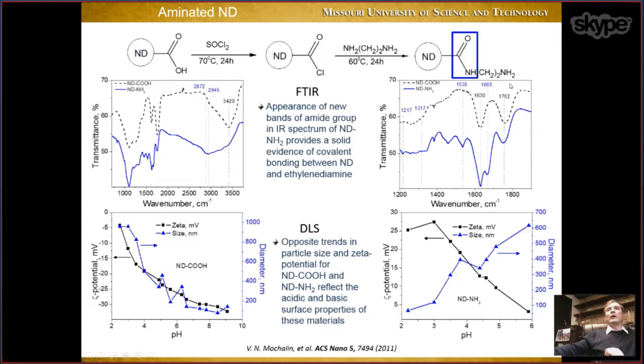And of course, since we now have amino groups on the surface, and here we had carboxyl groups, and you know that carboxyl group is acidic, amino group is a basic group, so we expect different behavior when we titrate these materials at different pH. And this is exactly what we see. Zeta potential and size behave totally differently for carboxylated material and aminated material when we change pH. So carboxylated material, for example, becomes much better dispersed at basic pH because these groups dissociate at basic pH and we have a negatively charged surface. And then since all nanodiamond particles have the same negative charge, they repel each other and stay dispersed.